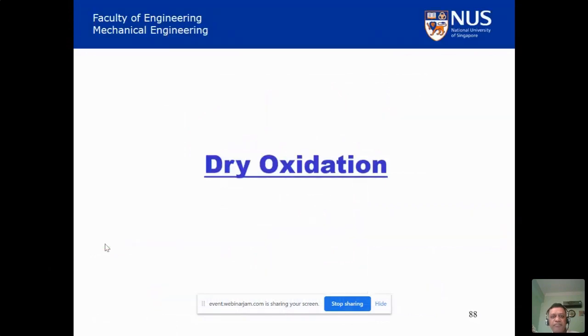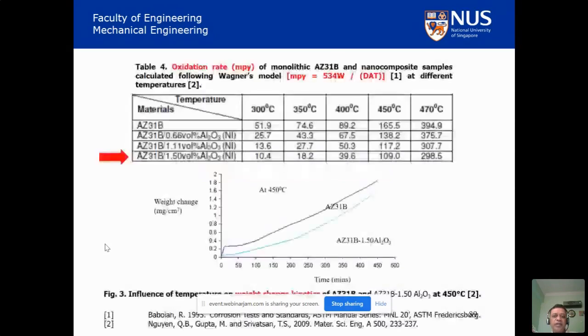We also sent in future some of the samples to Newcastle University, with the office in UK and Singapore, and they tested a number of magnesium-based composites, and they say the cutting force of all the nanocomposites is lower except for one material, which was magnesium 2.5ZnO. And that means if the cutting force is less, machining speed is high, again, your product can be made faster from this material. Corrosion is another issue which has to be considered for material selection.